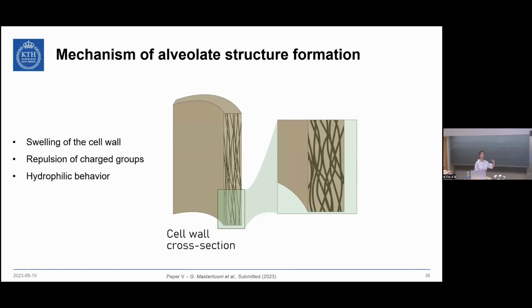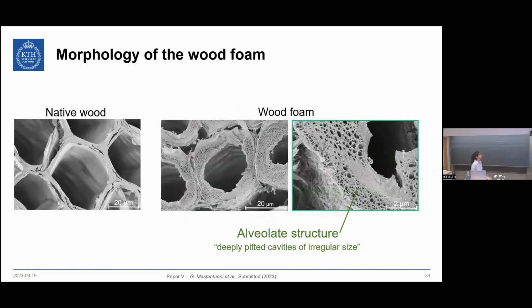So once we put the sample on top of liquid nitrogen, it's expected that the ice crystals will be able to grow along the longitudinal direction. And the more the material freezes, the longer these crystals grow. Then the crystals are removed by lyophilization, freeze drying of the material, leaving these parallel channels inside the cell wall. How these channels actually look, we can see from SEM.